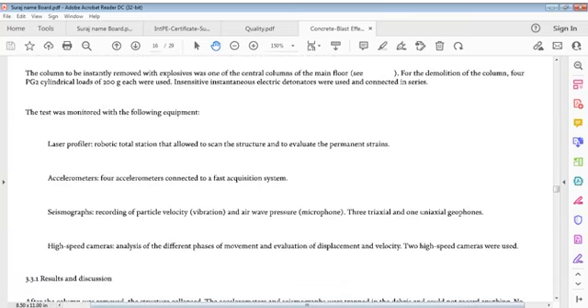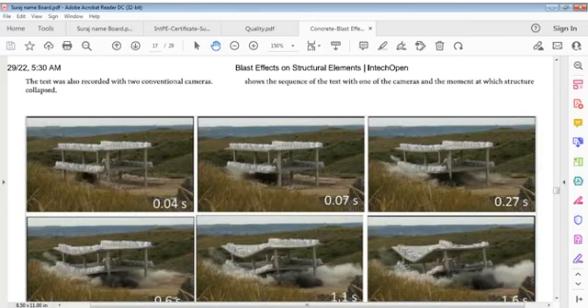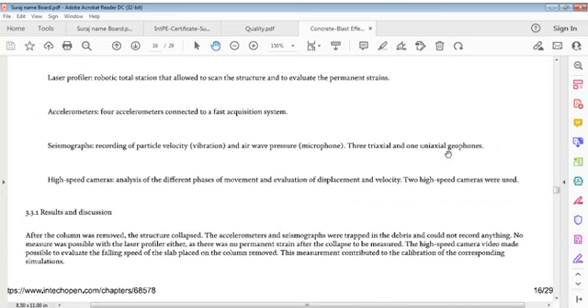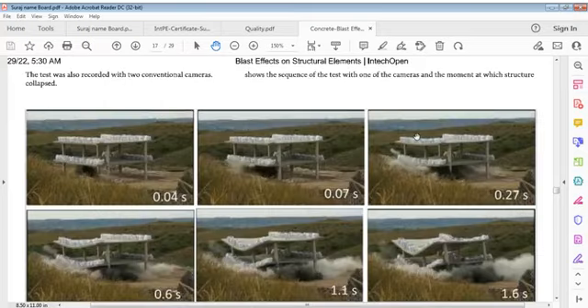The test was monitored with the following equipment. Laser profile, a robotic total station that allowed scanning the structure and evaluating permanent strains. Accelerometers, 4 accelerometers connected to a fast acquisition system. Seismographs, recording particle velocity and airwave pressure, with a microphone and three triaxial and one uniaxial geophones. High-speed cameras for analysis of different phases of the event and evaluation of displacement and velocity. Two high-speed cameras were used.